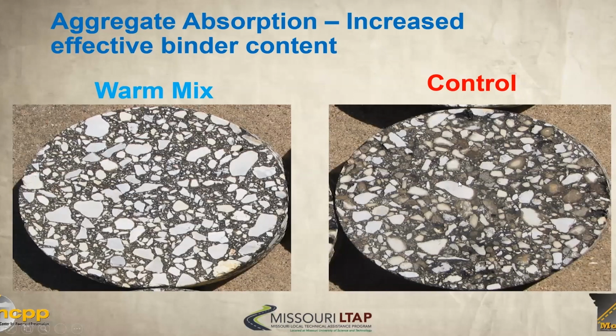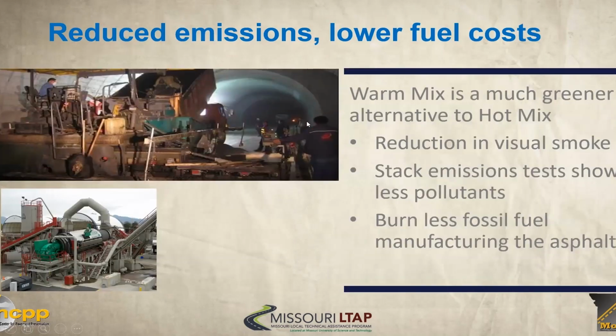The other thing is that the hotter you have the aggregate, the more absorptive it can become. So asphalt contractors have figured this out, and so they can actually reduce by maybe a few tenths of a percentage the amount of asphalt binder required to achieve the same results. So you can see in this core, we have hot mix and then warm mix, which is really fascinating. Obviously much greener. If you looked at a tunnel with hot mix, it'd be full of smoke. So stack emissions test. I've talked to asphalt contractors here in Florida where when they're running a stack test for pollutants, they run warm mix. So make sure they run it because they get much better results.